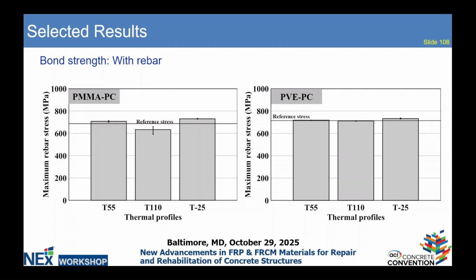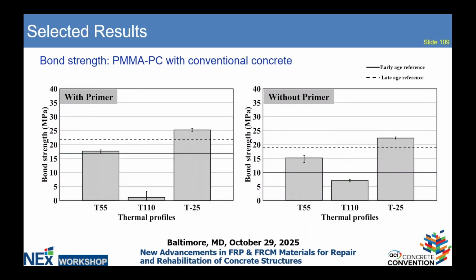Now, the bond with rebar also didn't change. The temperature conditions did not do much to the bond with rebar, except for the 110 case where there was a minimal drop in bond strength or the maximum rebar stress in case of PMMAPC.